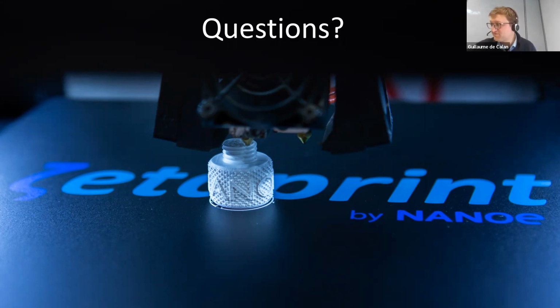We've made significantly big parts. To give you an example here, this part was done for a customer, and it's actually only infill, but the infill is 98%. So this does make for a very dense and very solid part, but the 2% of porosities are already enough to help for debinding. If I had to do this part of that size, a few centimeters by a few centimeters fully dense, I would never do that by 3D printing. I couldn't do it. And 98% density we can, because we usually use those 2% of porosity to help for debinding and sintering.